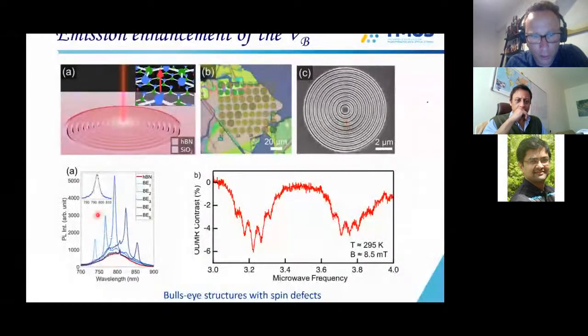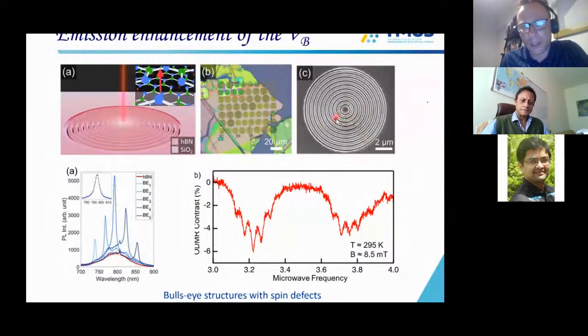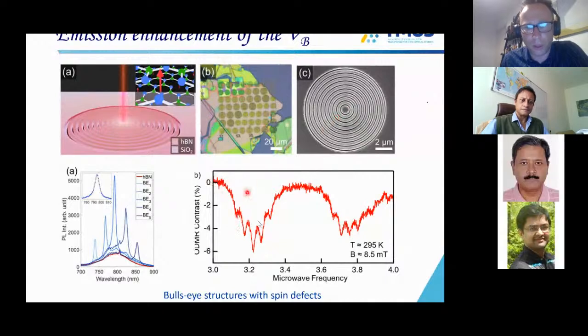And so you can see here that a pristine hBN, this is the red curve here, only gives you about 1,000 counts, and a bullseye structure gives you about 5 times more. So experimentally, we are only a factor of 2 away from a theoretical limit. And then because we can make these spin structures in the middle of the bullseye, we can make the ODMR contrast much better. You can see here it goes to 6%, and the more it goes down, the better the contrast, which means the faster you can do your measurements.